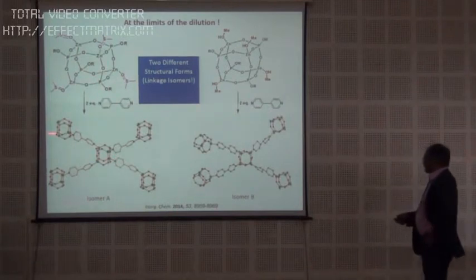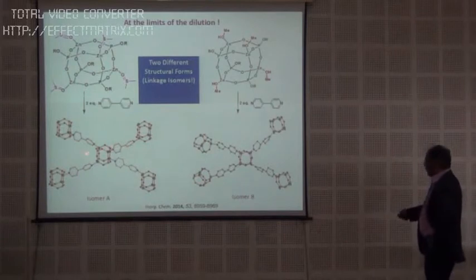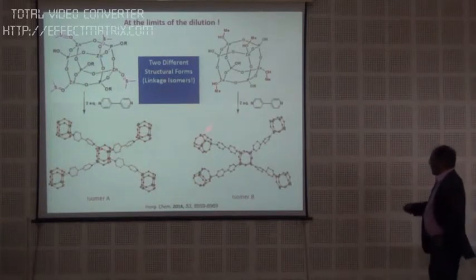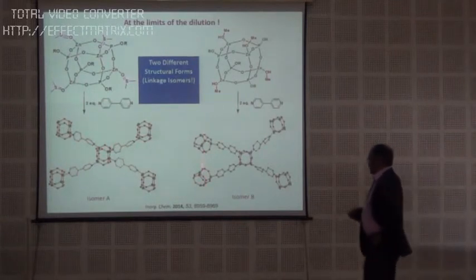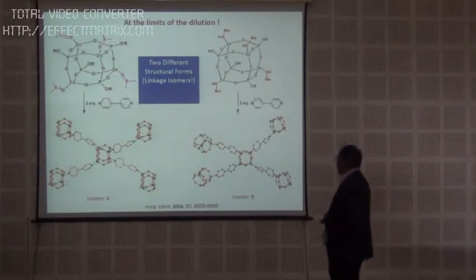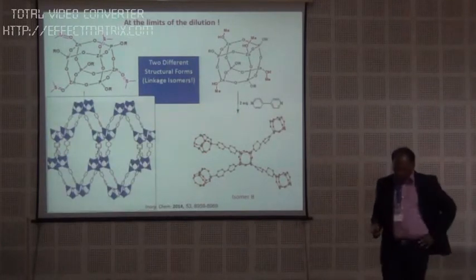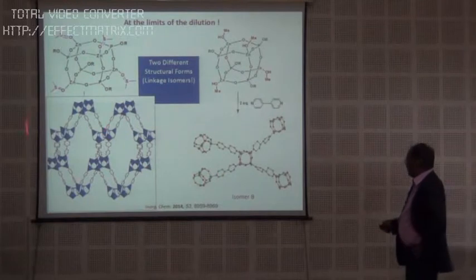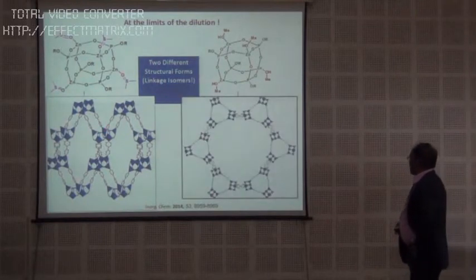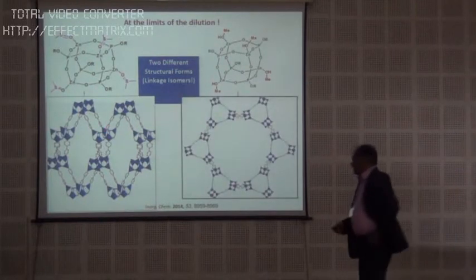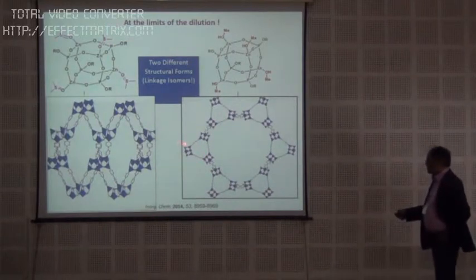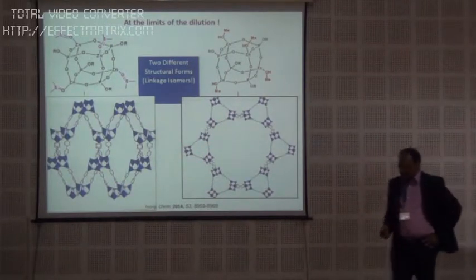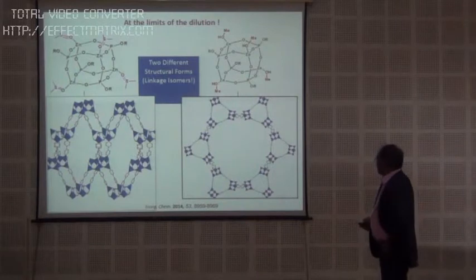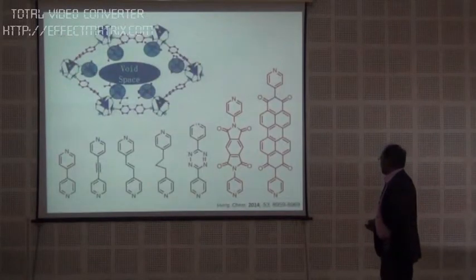Then we connected 1 cubane to 4 cubanes through these bipyridine bridges. Depending on how we place these cubanes with respect to each other, we can make isomeric compounds. For example, you can either have a diamond-like framework solid, which is this, or even you can have a Kagome type lattice where you have a micropore, which is about 7 angstroms, or a mesopore, which is about 30 to 40 angstroms.